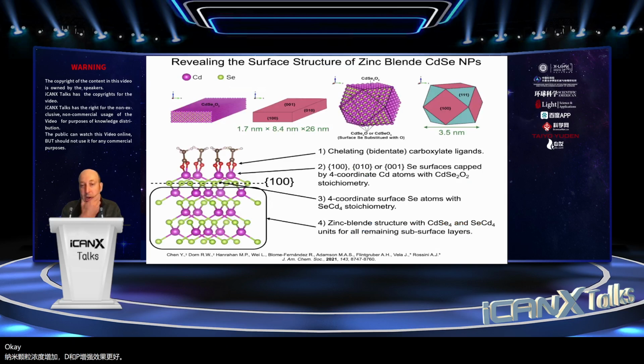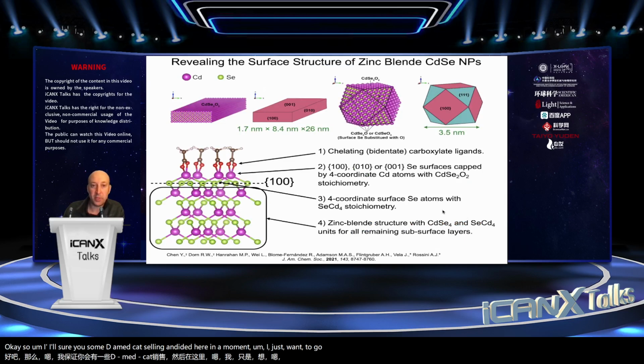Okay, so I'll show you some DNP data for cadmium selenide here in a moment. I just want to go through this really quickly and show that with NMR, we can really get precise, detailed structural models of what's happening. What does the surface of a nanoparticle look like? So in this project, we've looked at these cadmium selenide 2D plates and these spherical cadmium selenide particles. Now we know that plates should have this 001 type facet terminating it. For spheres, we think we also mainly have this 100 family of facets or surfaces. In addition, our NMR data would suggest that we have these 111 facets.